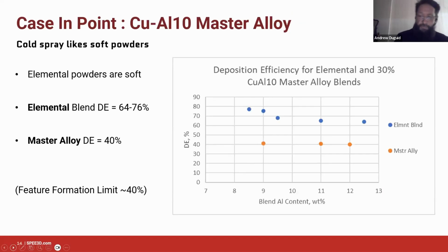Okay, so our observation right from the start, almost inadvertently, is that everybody starts out cold spraying elemental powders, because elemental powders are soft and easy to spray. And so we've developed a methodology where we look at either spraying blends of elemental powders or spraying combinations of master alloys. So we take the basic alloy and break it down into more cold sprayable components. That might be splitting the alloying elements into two major groups and spraying a blend of two powders that each have some of the alloy constituents in them. Or it might be breaking the alloy down completely and just spraying a blend of elemental powders.